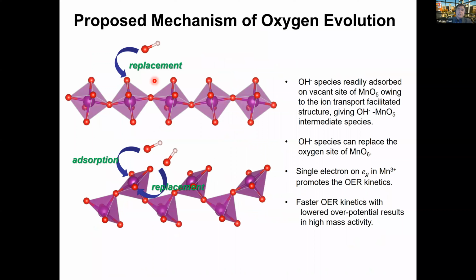So these are the two features at the time we thought were going on in this particular type of complex oxide structure and why it helps, at the structural level, the oxygen evolution reaction. Instead of having to knock off atoms at the octahedral site on the surface, it naturally has a lot of these sites already available on the surface as well, which could favor the adsorption of the active group, for example the OH group, on the surfaces. So that's why we very early on thought about this particular system.